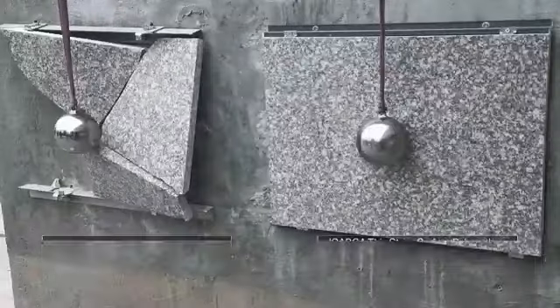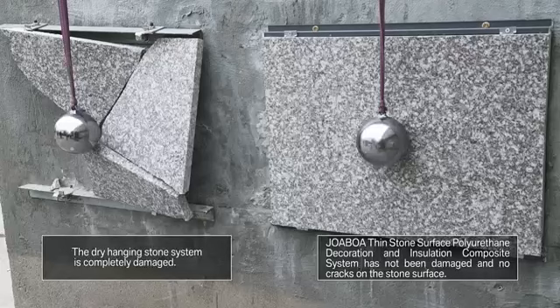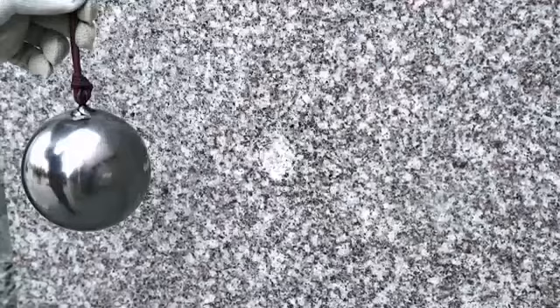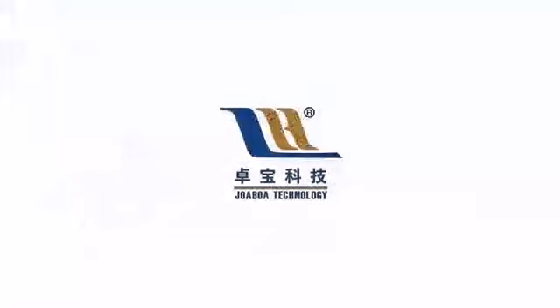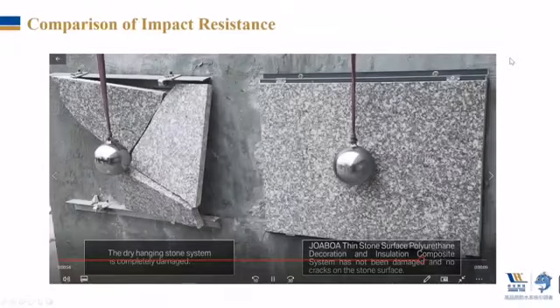So in the end, we can see, for the traditional stone curtain wall system, it has been completely smashed, but the impact only leaves a small crater on the surface of Joaboa stone system. The difference here shows our system can have a better impact resistance than traditional system. But how about the reason? The reason is that we have an insulation layer, which also can work as an excellent supporting and buffer layer to absorb the impact force.